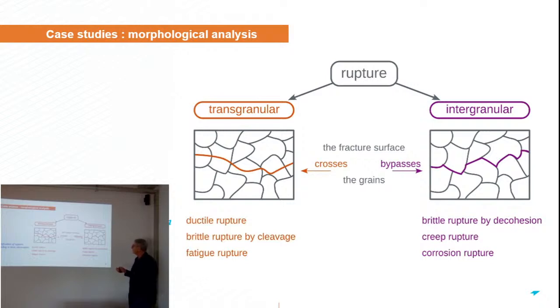So the fracture in a material can be either transgranular, when the fracture surface crosses the grains of the material, or intergranular, when the fracture surface bypasses the grains. The intergranular failures are brittle rupture by decohesion, creep rupture, and corrosion rupture. And the transgranular fractures are ductile rupture, brittle rupture by cleavage, or fatigue rupture. You can also consider the fracture surface by its observation or its kinetics. Fracture can be either instantaneous or progressive. Instantaneous in the case of ductile, or brittle by cleavage or by decohesion fracture, and progressive in the case of fatigue, creep, and corrosion as well.